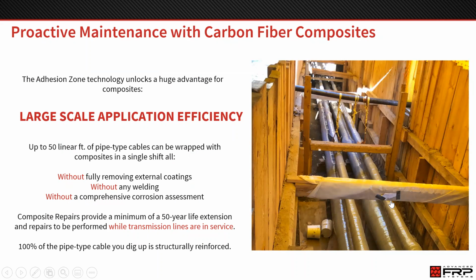So we looked at 2 scenarios, one using external welds and the other using a composite, and they're fairly similar. Some distinct differences and some advantages of the composite, but I want to highlight one really important point of the composite repairs. It's this adhesion zone technology. I touched on it on the last slide. What this means is it's really efficient to do large-scale repairs with composites. The exact opposite of welded repairs, where it's really efficient to do a small welded repair, but large repairs are difficult. We can wrap up to 50 linear feet of cable in a single shift without fully removing the external coating, without any welding, and without performing a comprehensive corrosion assessment.